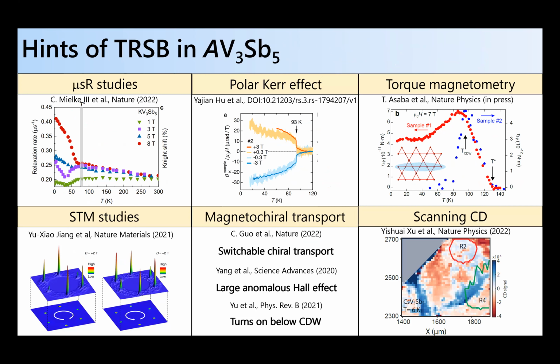So what's going on in terms of perhaps an imaginary component or predictions of realizing this orbital antiferromagnetic state? What makes the charge density wave state interesting is that there are hints of time reversal symmetry being broken in the CDW state from a variety of different probes. The initial hints were STM studies, where by looking at the STM Fourier transform of the charge ordered state, it seemed to respond to the application of a magnetic field. μSR seems to see some uptick or a change in the muon spin relaxation rate upon entering the CDW state. There are hints in magnetotransport of either inversion symmetry or time reversal symmetry being broken. There's a large anomalous Hall effect with no spontaneous component. So whatever we want to call that, an anomalous, weird Hall effect.